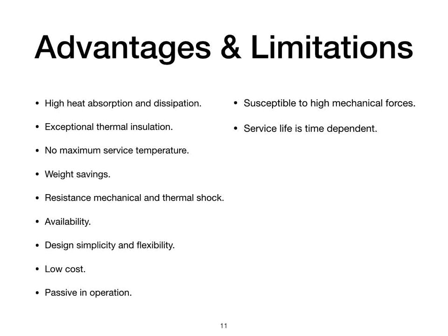Ablative materials absorb and dissipate high heat loads with minimum surface erosion and provide excellent thermal insulation of the substrate. They have no upper surface temperature limit and they can accommodate virtually any operational temperature by controlled material degradation. They are usually light and vary from about 10 pounds per cubic foot for foam plastic to over 200 pounds per cubic foot for metal fiber reinforced ceramics.